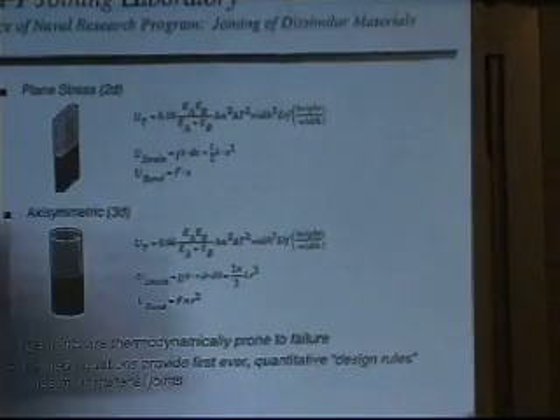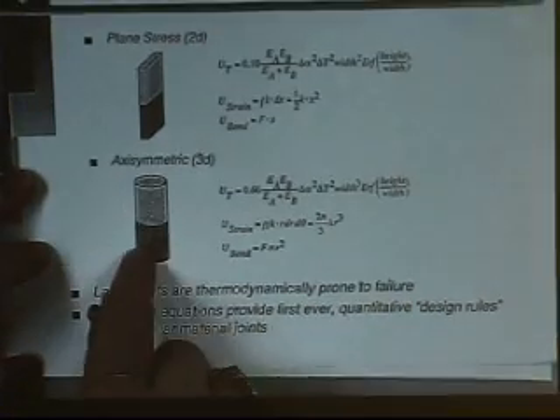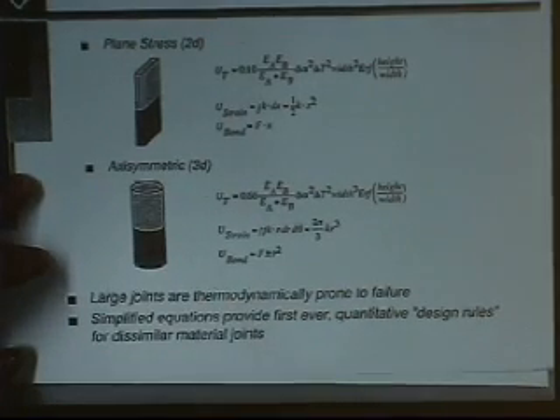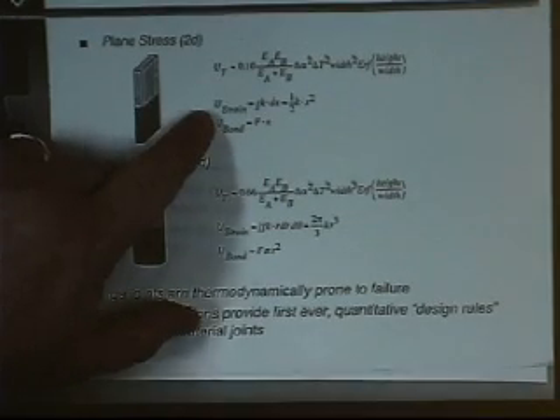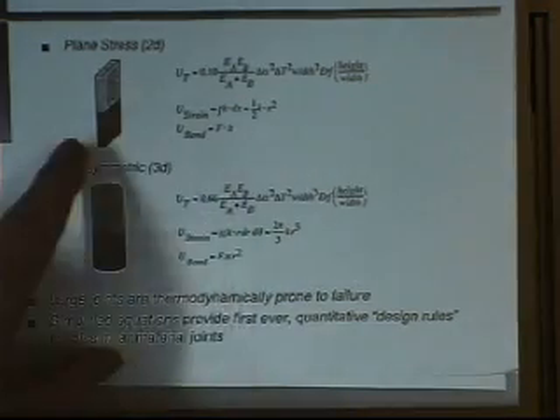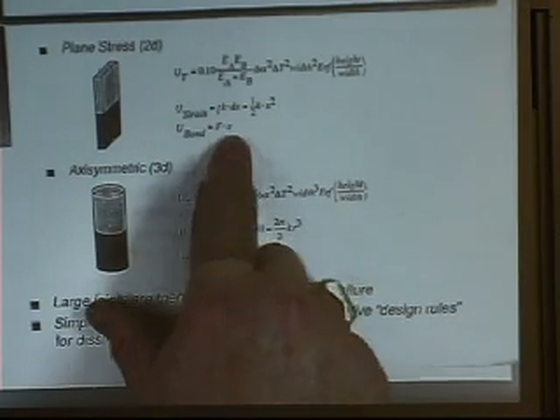But basically, if I look at joining two dissimilar materials and I look at thin sheets of material, so my big buildup of stresses is only in one dimension, or if I look at something axisymmetric, where my stress pattern across that interface is going to be in both dimensions, it turns out that the strain energy, in this case, in the plane strain stress case, goes as 1/2 kx squared, where x is the long dimension, but the bond strength only goes by the strength of the bond, F times that dimension. Actually, it's F times x times 1, but if we're just talking unit dimension thickness. So the strength goes as x, but the strain energy that you're building up goes as x squared.